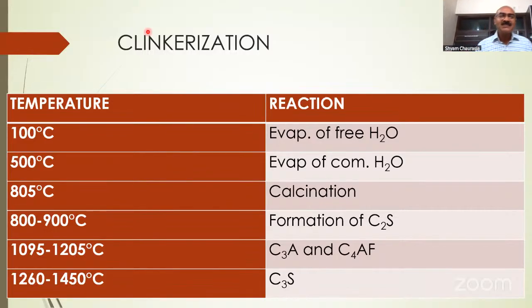This process is called calcination. At around 800 degrees centigrade, this calcination reaction starts. It liberates carbon dioxide from the calcium carbonate of the limestone and leaves CaO, that's a reactive calcium oxide.